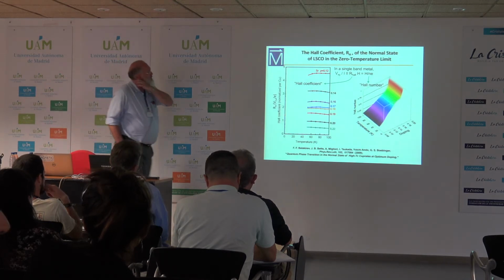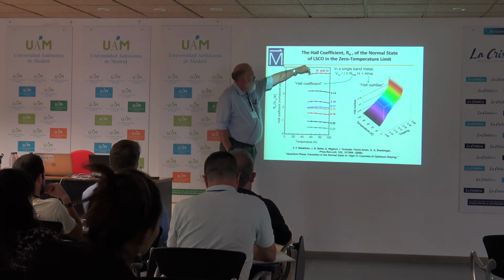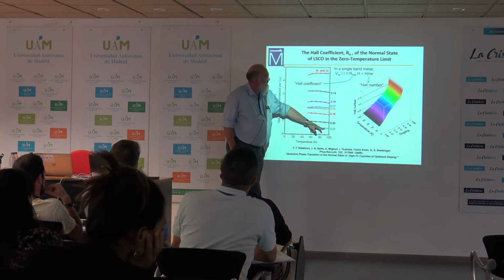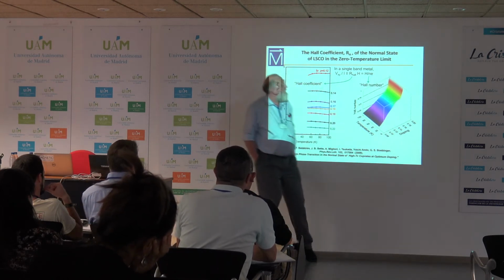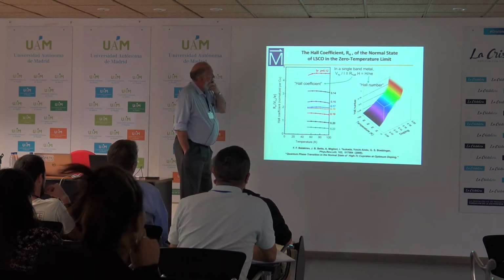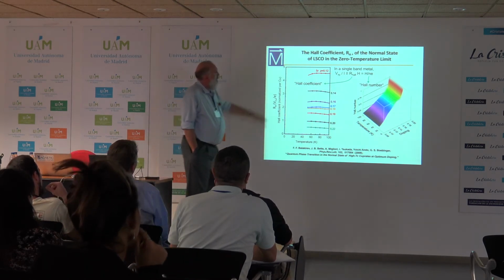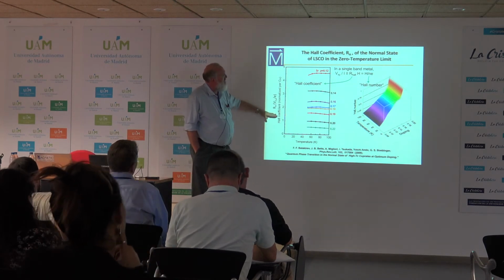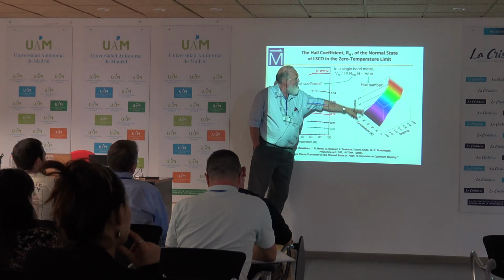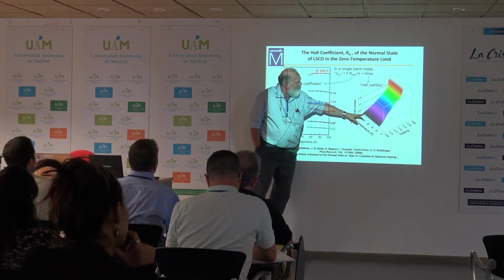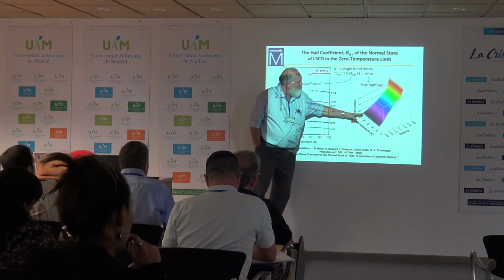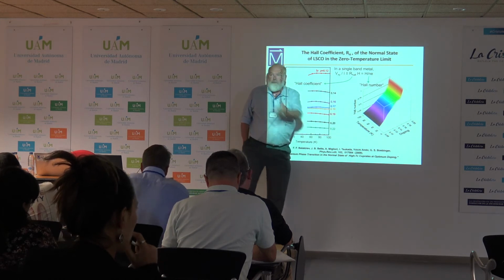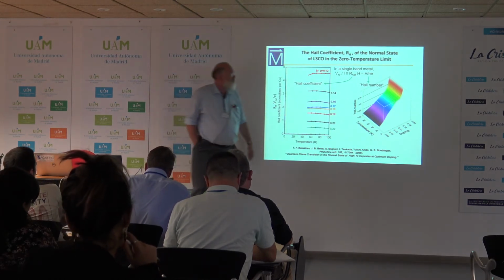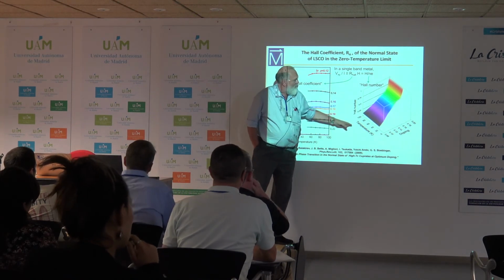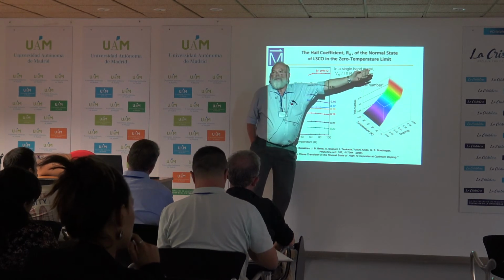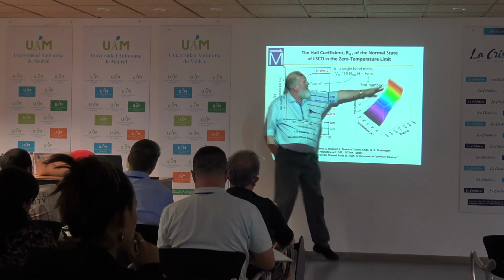Well, when we measure the Hall coefficient at relatively high temperatures above 50 Kelvin for different strontium dopings, so we're going from here up to there, it's a monotonic behavior, and there's not anything that's particularly special there. What we've done is we've measured the Hall coefficient, plotted it here, and then we normalize the Hall number so it's carriers per copper. So it's sort of a logical way to interpret, and you'll notice that in the 0.08 sample, you've got 0.08 carriers measured per copper. And in fact, in some data that was in the previous talk, Yoichi Ando's group measured in this regime, and the Hall number is just tracking your doping perfectly. Well, here it's screaming up. And there was some discussion in the previous talk about whether we're going from P to 1 plus P.